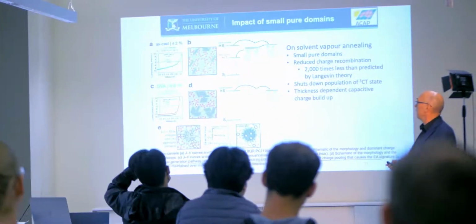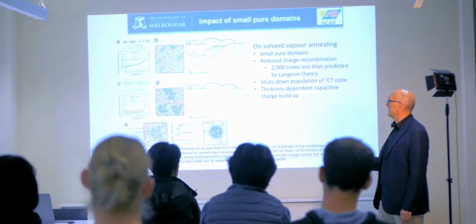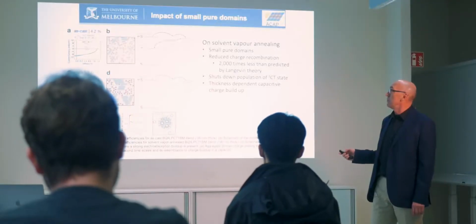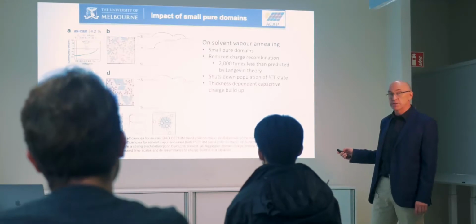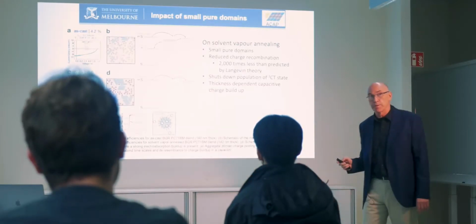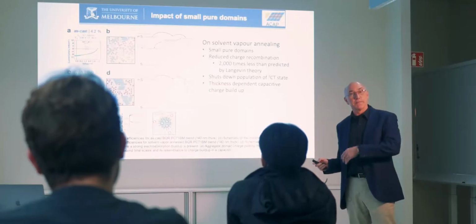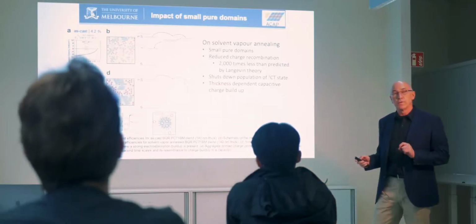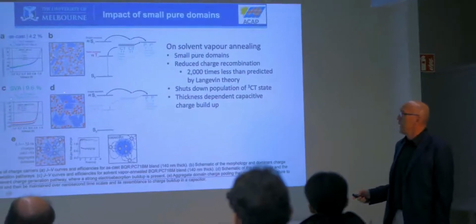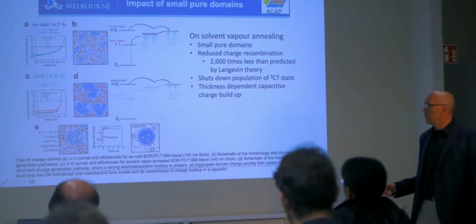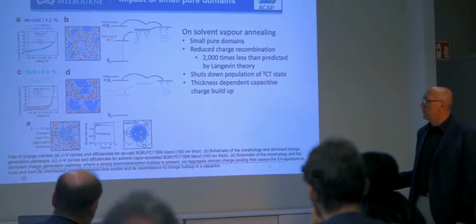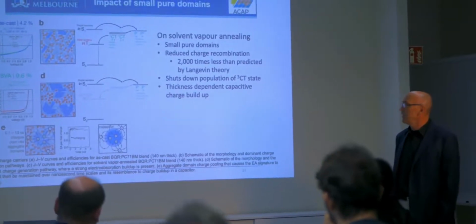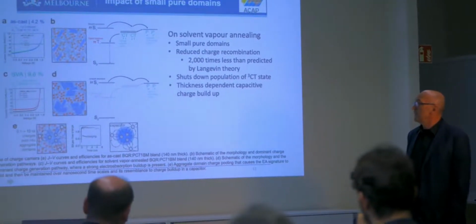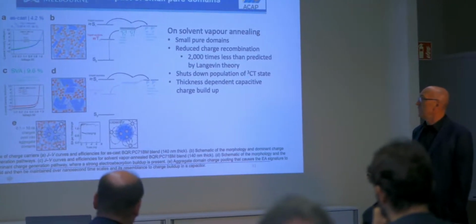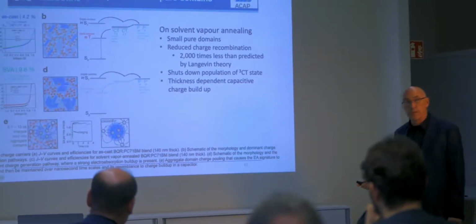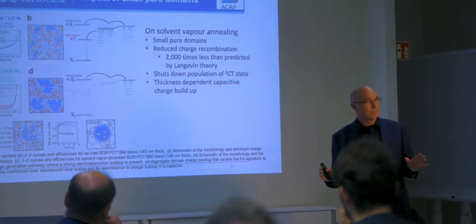And if we look at this, we see that in the unannealed film, we must be generating triplet CT states, charge transfer states, because we populate the triplet level of the donor. And that's a loss mechanism. And so that's what we don't want to have happen. However, as soon as we anneal the film, what we end up getting is very, very pure domains from all the data we've got, small domains, and we get very pure domains. Now what happens is we generate these electrons and holes, and they stay there.